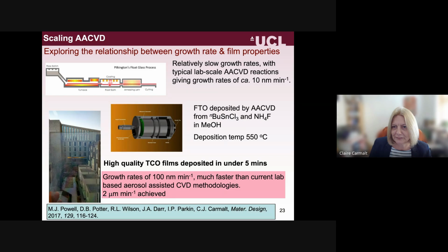So lab scale AACVD reactions really give quite slow growth rates. The growth rates are about 10 nanometers per minute, using the ultrasonic form of forming the aerosols. So we did quite a lot of studies. We used fluorine doped tin oxide because we just wanted to grow an easy film, to understand the growth rates rather than changing the properties. And you can grow that using butyl tin trichloride with dopant amounts of ammonium fluoride and methanol. We had the temperature at 550.